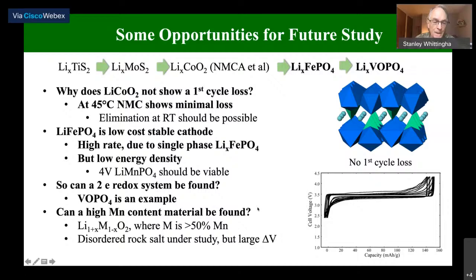As I mentioned earlier, the ideal would be to have a high manganese content material, and people are looking at that now. And Argonne National Lab looked at a long time at lithium-rich, manganese-rich materials, which had more than 50% manganese, but they had low stability. Others are looking at disordered rock salt versions of this material, but they have a very high voltage change, not a nice plateau like over here.